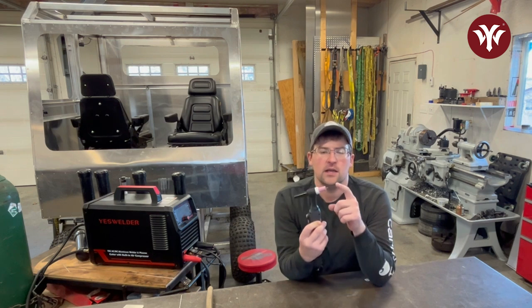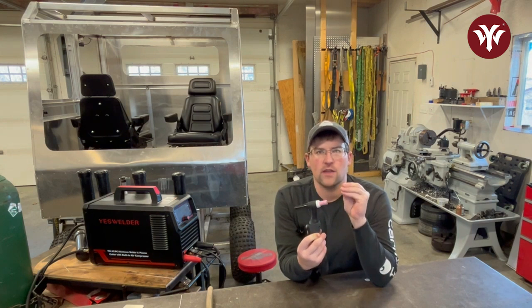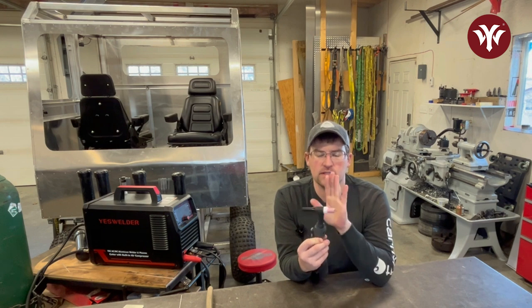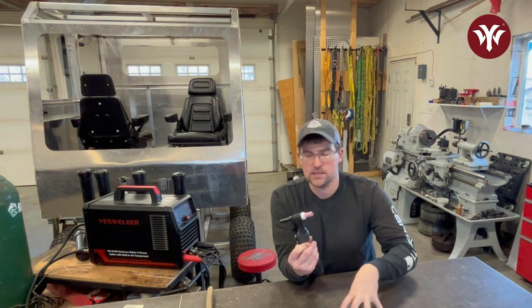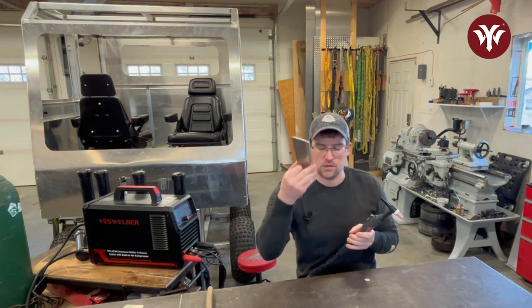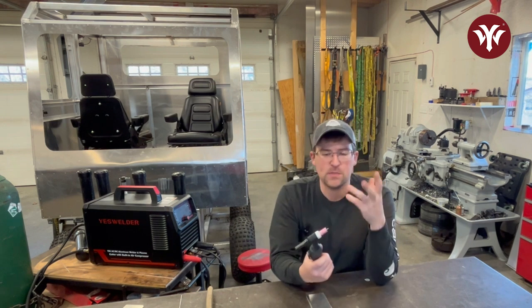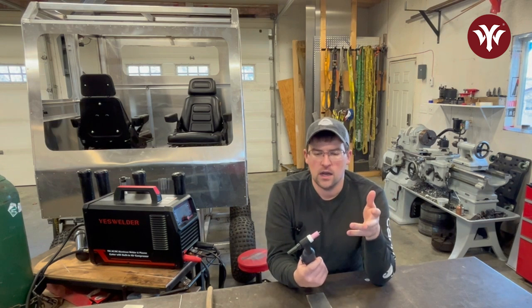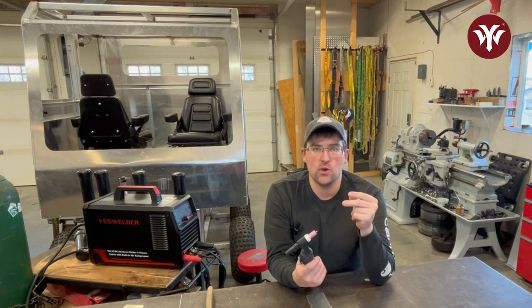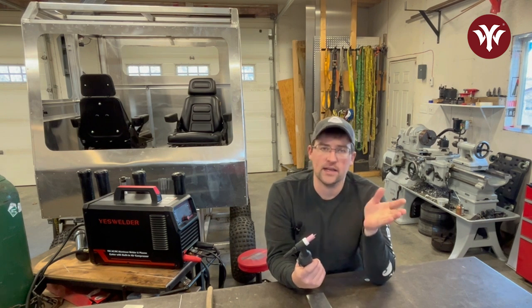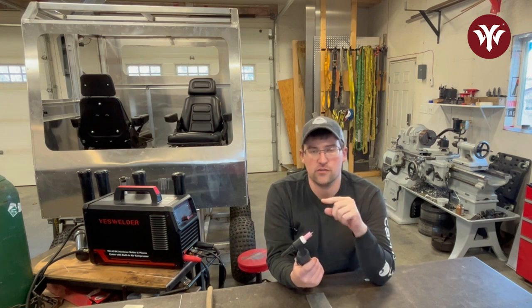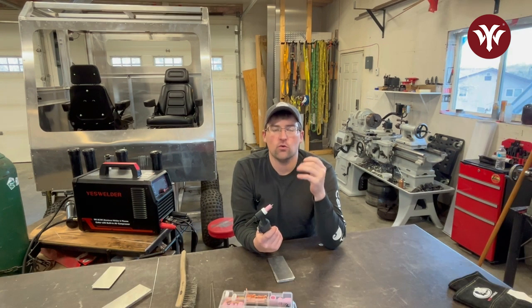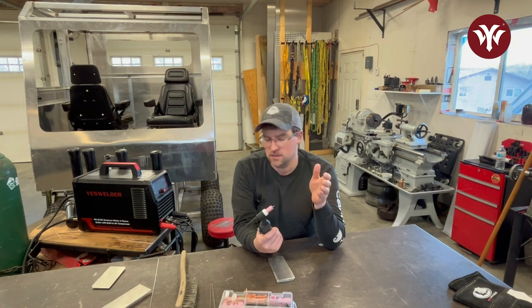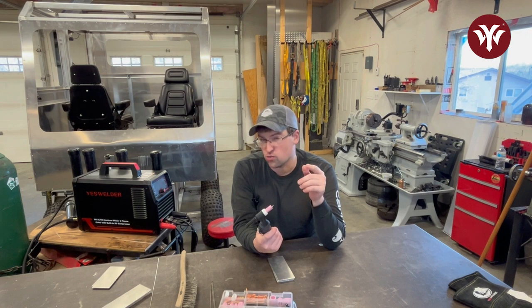If you're new to TIG welding, tungsten is the electrode that's used to transfer the arc between the TIG torch and your workpiece, the base metal. In this case, it's going to be aluminum. And there are many different types of tungstens out there. The two common types that I'm always going to for AC TIG welding, and also DC, because these two can be used for either, are a 1.5 or 2% lanthanated tungsten, which I think is often gray.